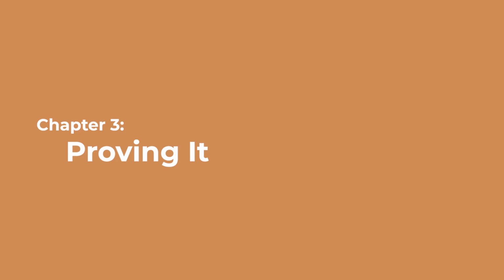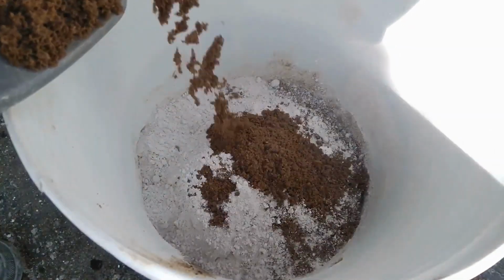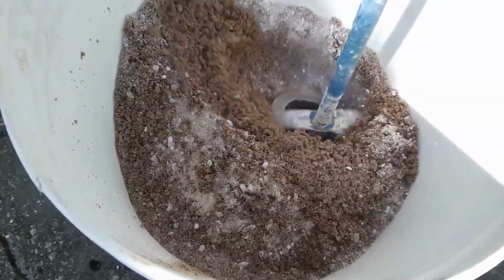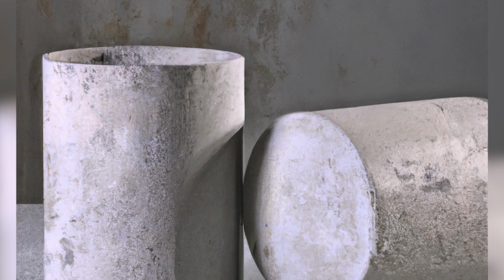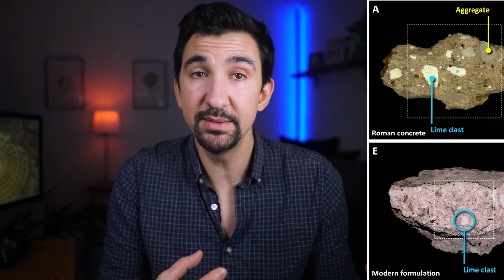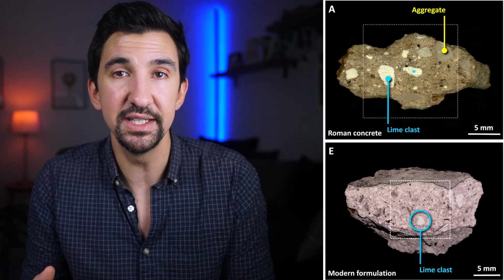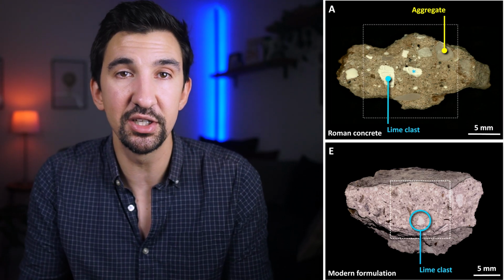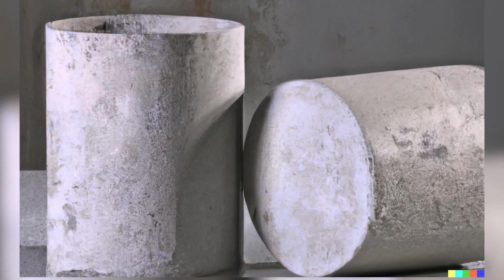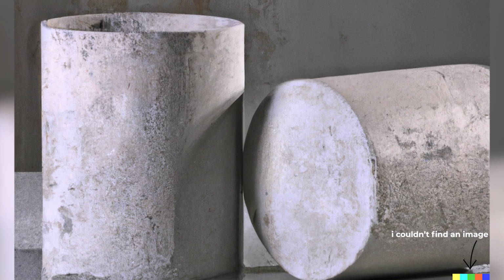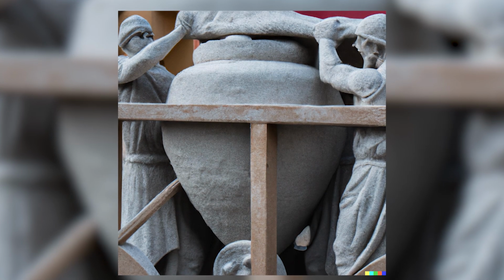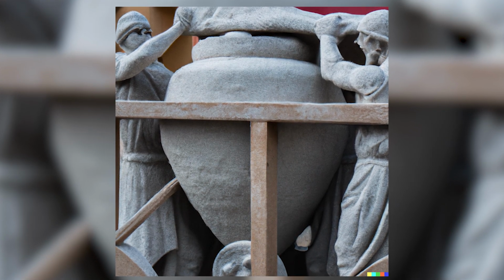To prove beyond a reasonable doubt that this indeed was the mechanism responsible for the durability of Roman concrete, the team set out to run an experiment. They produced samples of hot mixed concrete that incorporated both ancient as well as modern ingredients, as well as a set of controls that did not include quicklime. The team observed that the hot mixed concrete contained small white lime clasts throughout the form. But in the slaked mixture without quicklime, these clasts were absent, compelling evidence that this was in fact how Romans made their concrete.